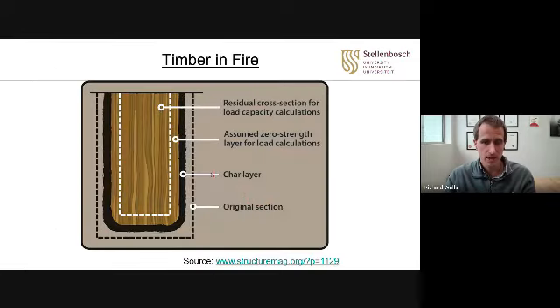Sorry, one thing I didn't mention is that earlier we discussed reaction to fire tests. So remember, reaction to fire is, can it burn? How does the fire spread? A timber beam can have a good fire resistance, but a poorer reaction to fire. So when a timber structure burns, it's going to release a lot of heat. So you will need to use a more severe design fire. Let's say you used to need a 30 minute fire rating, you may now need 60 minutes. Because now the skeleton of your structure, your beams and slabs and floors, contribute to the fuel, so they will burn more intensely. There you go.